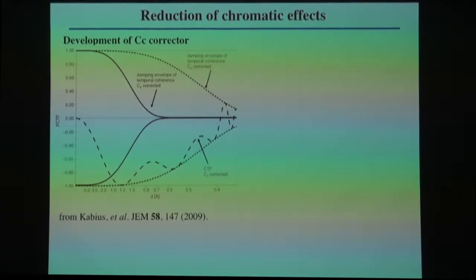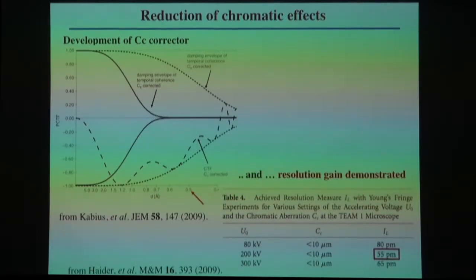Okay, so microscopes have overcome aberrations to a certain extent. Now we're going to be limited by the envelope functions. And the major envelope function that's hanging out there above our heads is chromatic effects. So Haider and colleagues developed a CC corrector at CEOS. And this is just showing what the transfer function would look like once it's CS and CC corrected. So this is the envelope. Here is one angstrom. You should be able to push way out to better than half an angstrom resolution. And in fact, once they applied the CC corrector, they were able to get, at 200 kV, out to 55 picometers. And so they were pushing very close to the half angstrom resolution.